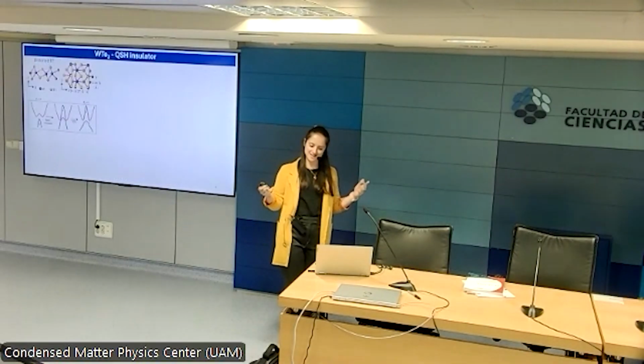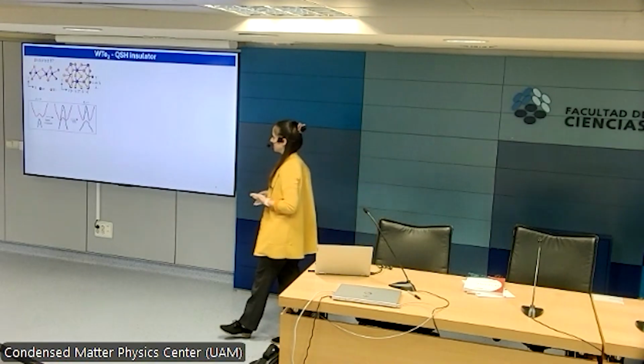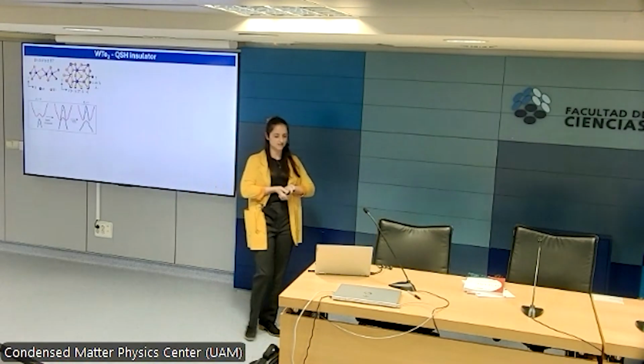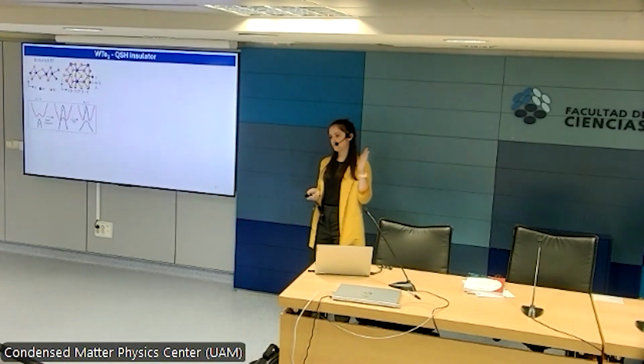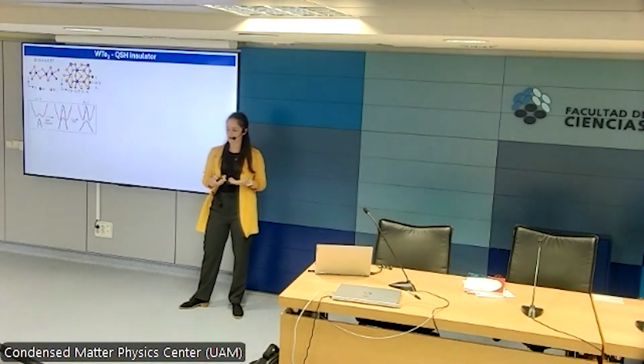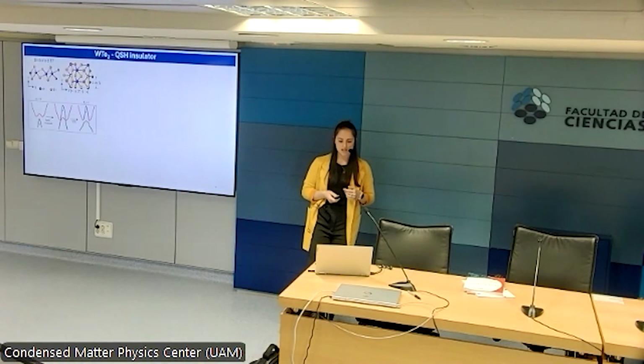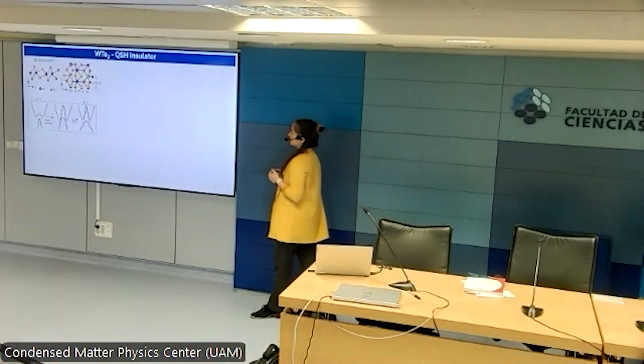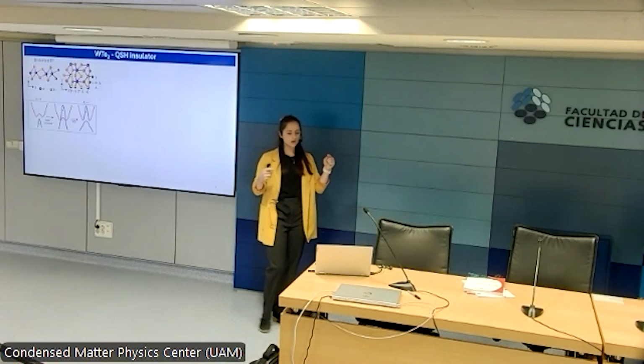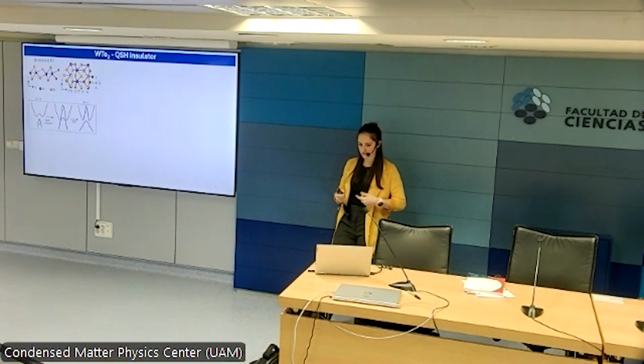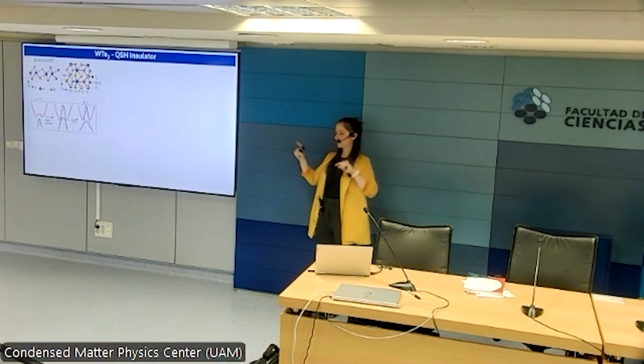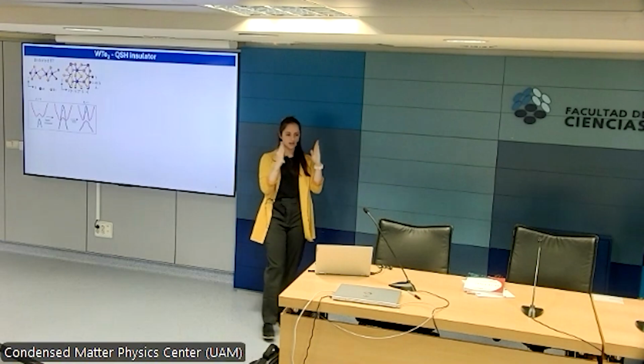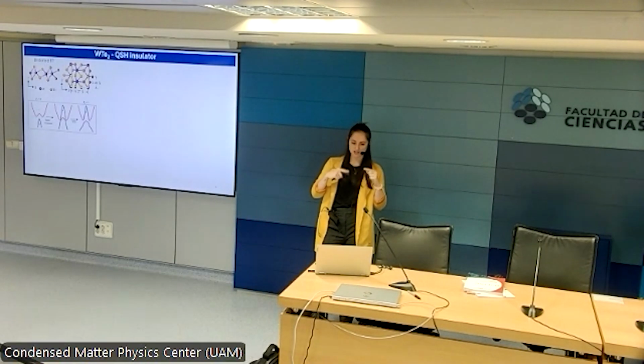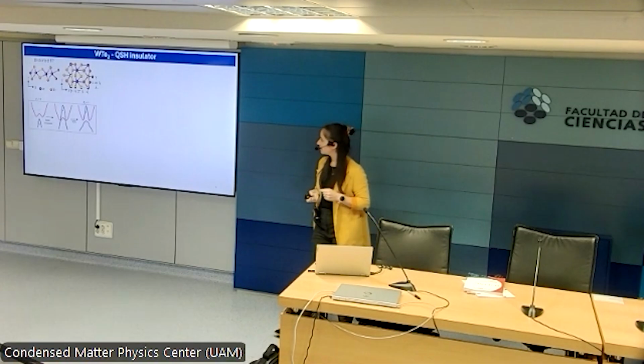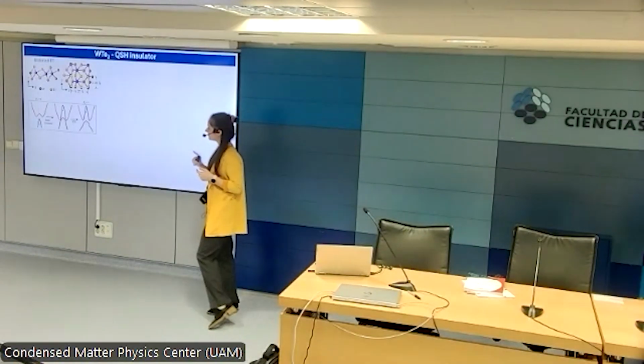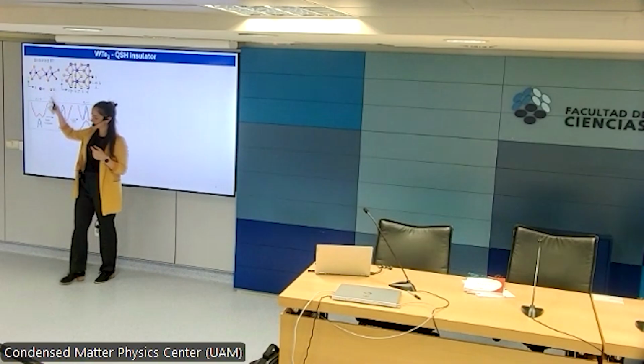Now, in the very remote case that some of you don't know what a transition metal dichalcogenide is, tungsten ditelluride is a member of the transition metal dichalcogenide family. Transition metal dichalcogenides are characterized by having a unit cell, which is the one that I'm depicting there. You have a transition metal layer, which is sandwiched between two chalcogen layers. And this specific transition metal dichalcogenide crystallizes in a structure that is known as the distorted 1T'. So compared to, for example, molybdenum disulfide, in moly disulfide, the molybdenum atoms are all equally spaced. In tungsten ditelluride, the tungsten atoms form dimerized chains, and the chalcogen layers arrange in a zigzag fashion in the direction perpendicular to the plane. This means that if you were to look at the material from the top, and this is important for the following, you would have alternating rows of high and low chalcogens zigzagging.